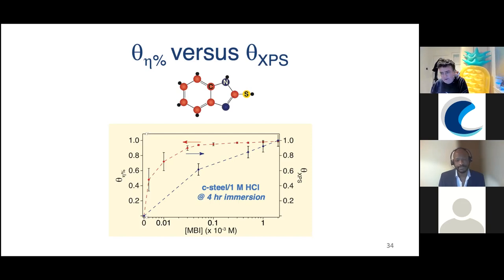We have some ideas how we could target that to increase the persistency of molecules on the surface, so they have longer residency times. One thing to say is that you don't want molecules that are too persistent, because you might have gaps between them where you start getting preferential corrosion. So you want a bit of dynamics. But if you could dose, instead of continuously, say once a day or once a week, or at a lower concentration, that would be commercially financially cheaper and also more environmentally sustainable. So I think persistency is a real area we should push forward with. True, very true.